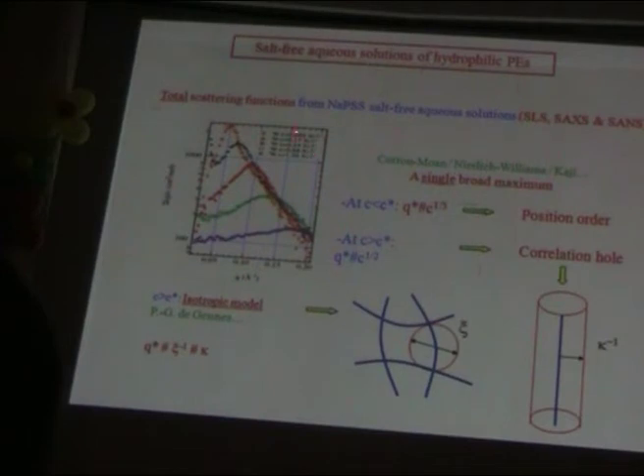Here you have the first result. If you look at the scattering intensity versus the scattering vector, you have this maximum, and of course the position of this maximum changes with the concentration. But not only with the concentration. That has been observed for the first time by these two persons, Cotton and Moan, and everybody has seen this maximum now.